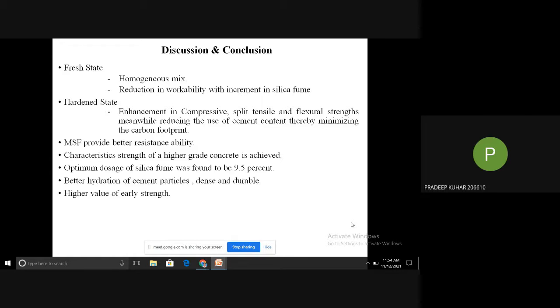it can be said that with the addition of silica fume in concrete, homogeneity gets enhanced, but there is a reduction in workability. So we can use superplasticizers to overcome the additional water requirements. Further, it was noted that specimens prepared using microsilica fume have better resistance against chemical attack when placed in 5% dilute hydrochloric acid solution for a period of 30 days. There is an enhancement in the concrete strengths, whether compressive, flexural or split tensile strength. Meanwhile, we are consuming less cement, therefore we are minimizing the carbon footprint also. And the optimum replacement amount was found to be around 9.5%.